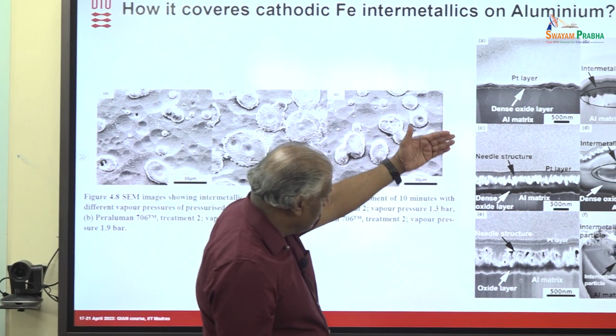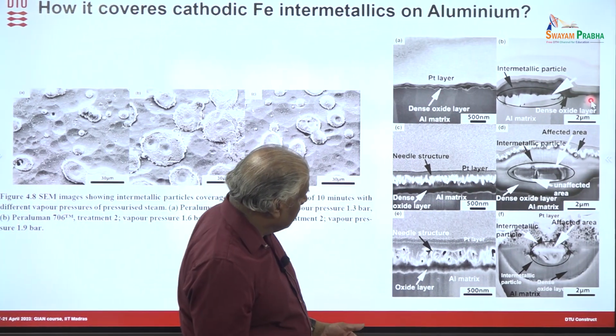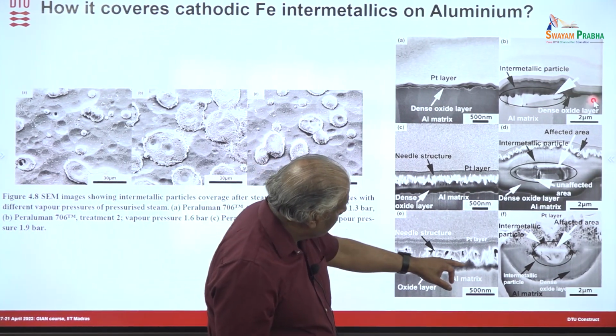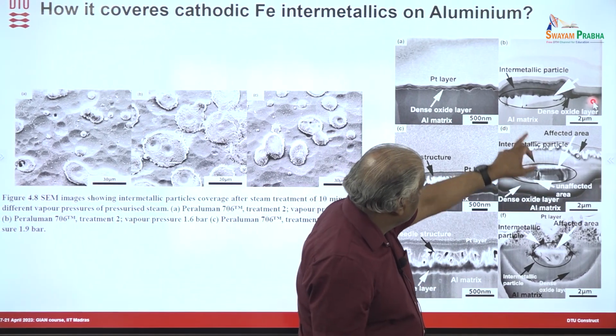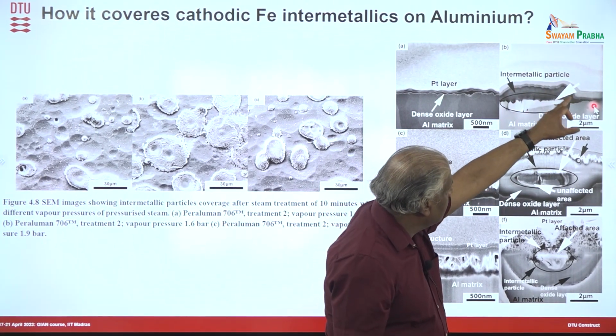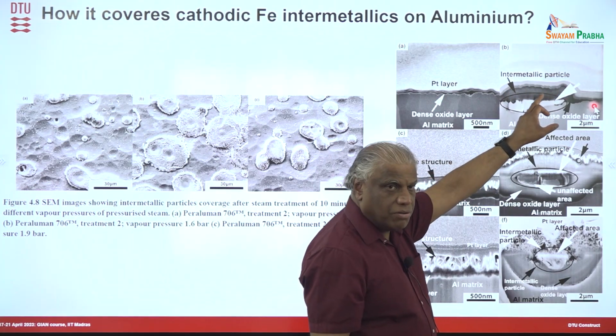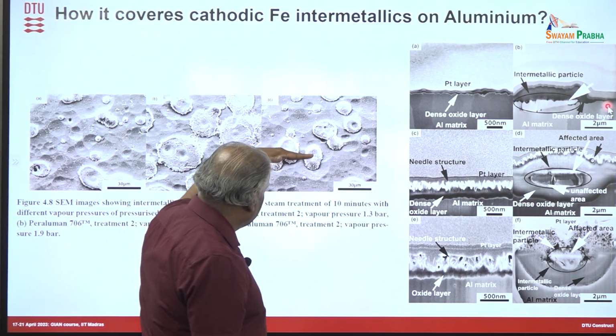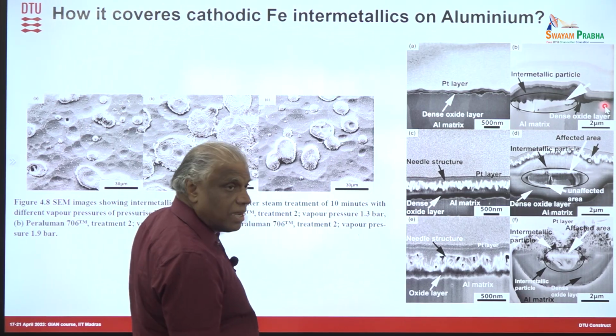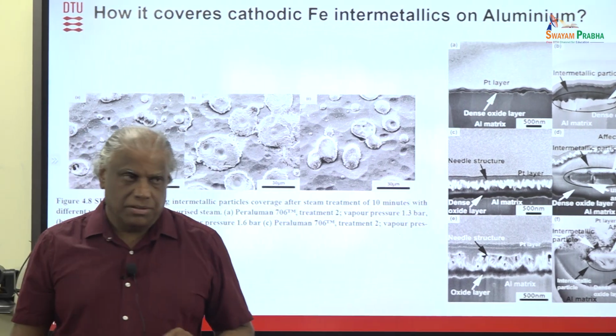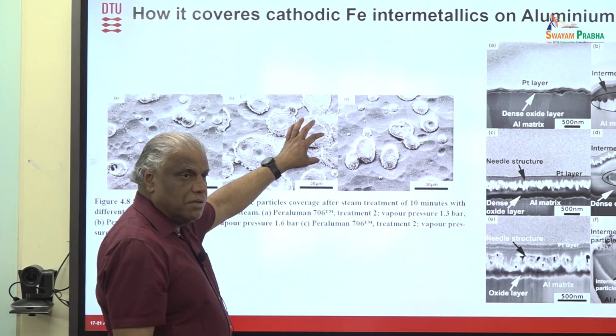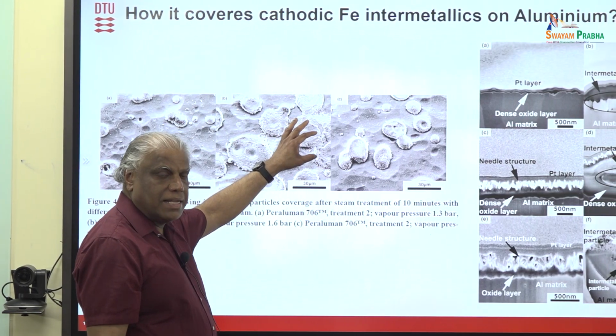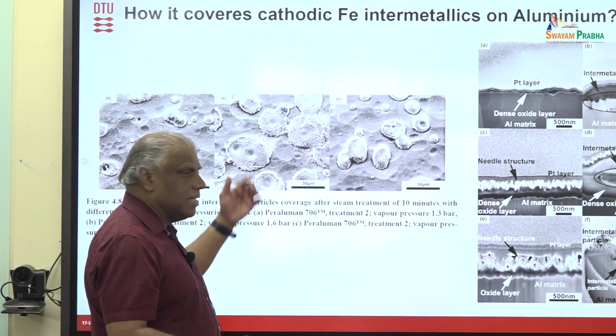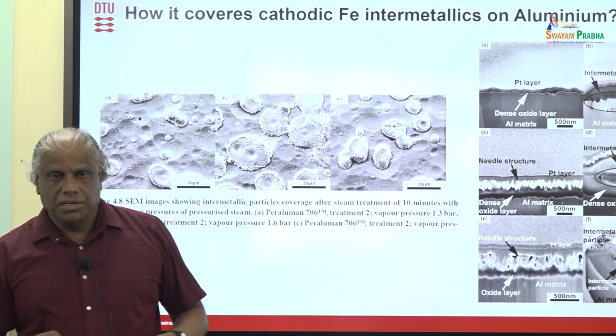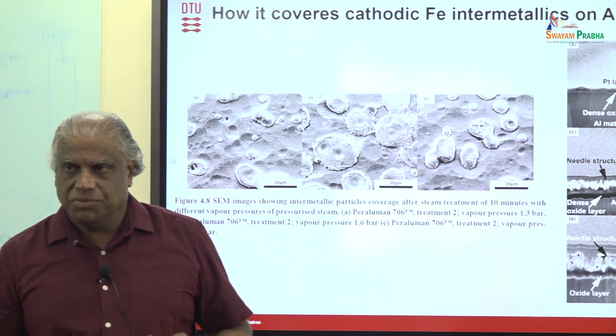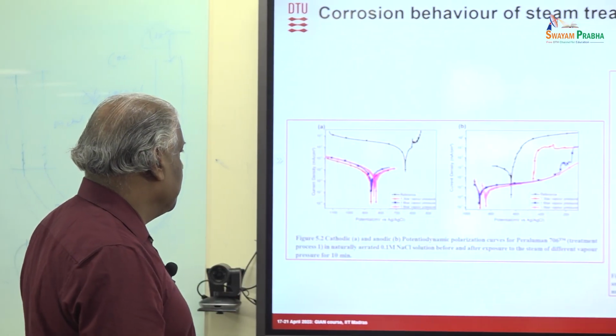That's what you also see in this FIB cross section. You can see this interface here with the coating covering the intermetallic particles very nicely. So all this cross section shows that if you take a cut here, it has very good coverage over the intermetallic particles. You can see that there is some special growth over the intermetallic particles, because intermetallic particles contain iron as well. So it grows iron oxide and aluminum oxide. So you have this special growth on the intermetallic particle. It is fully covered. The intermetallic particle is covered that way, which is a good coating.